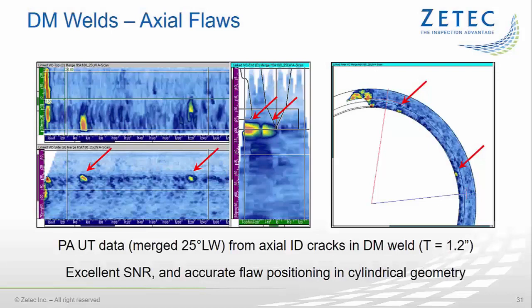This examination method is very effective for detection and sizing of axial flaws in austenitic components when the weld cap is ground flush. This slide shows the data obtained on a 14-inch diameter dissimilar metal weld with a wall thickness of 1.2 inch. In this case, the merged data from all skew angles for a refracted angle of 25 degrees are shown. This gives a very comprehensive image of the 2 flaw indications. The L-wave beams provide excellent detection capability with a high signal-to-noise ratio, and the polar view shows accurate positioning of the flaws in the cylindrical geometry.